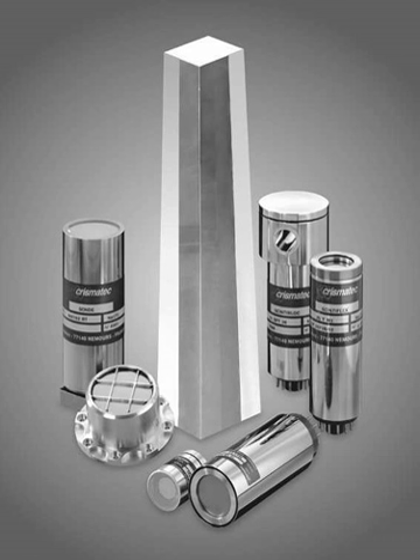Liquid scintillators are easily loaded with other additives such as wavelength shifters to match the spectral sensitivity range of a particular PMT, or 10B to increase the neutron detection efficiency of the scintillation counter itself, since 10B has a high interaction cross-section with thermal neutrons. For many liquids, dissolved oxygen can act as a quenching agent and lead to reduced light output, hence the necessity to seal the solution in an oxygen-free, airtight enclosure.